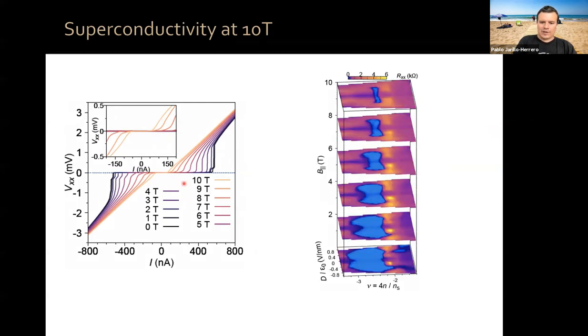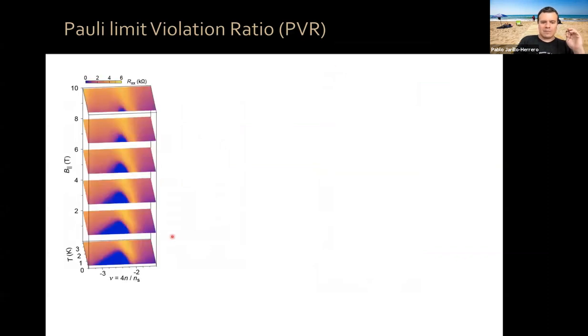Indeed, it survives. We can look at the zoom in of the resistivity versus filling factor and displacement field at 0, 2, 4, 6, 8, 10 Tesla. Indeed, there's an extended region. We can watch it shrink, okay? In order to see by how much we violate the Pauli limit, we need to do temperature-dependent measurements. So we can measure here at optimal displacement field as a function of filling factor or density. So this is the usual superconducting dome. And now we can measure the superconducting dome as a function of parallel magnetic field, and we see that at 10 Tesla, there's still a finite